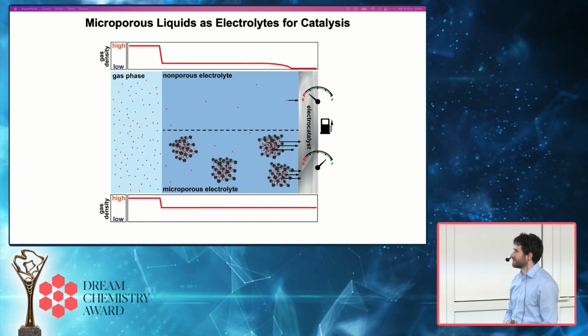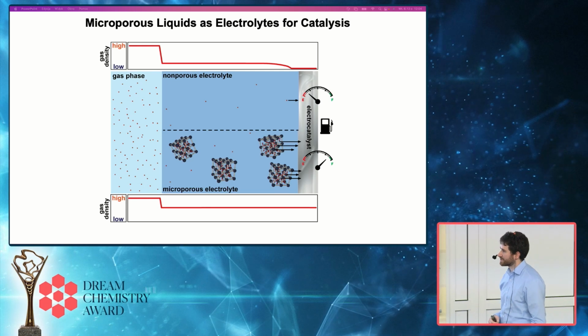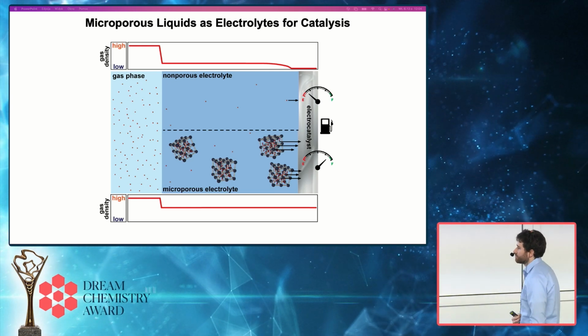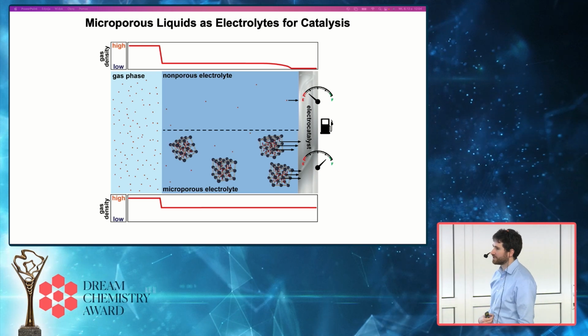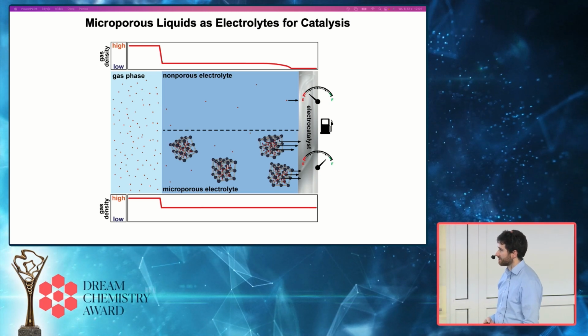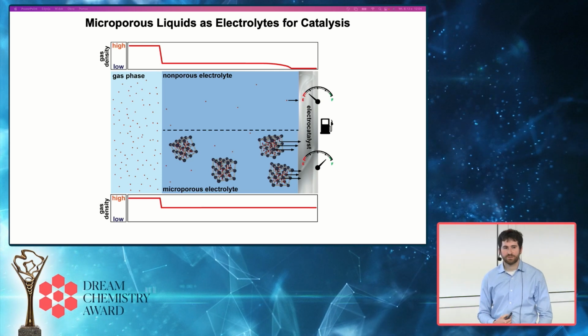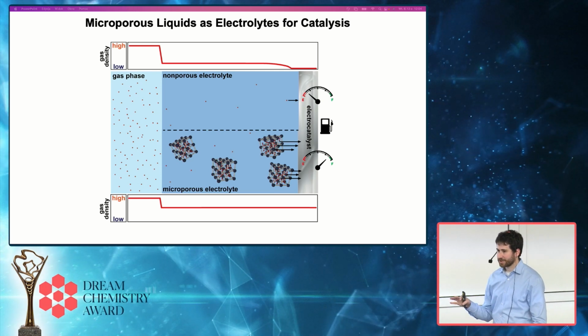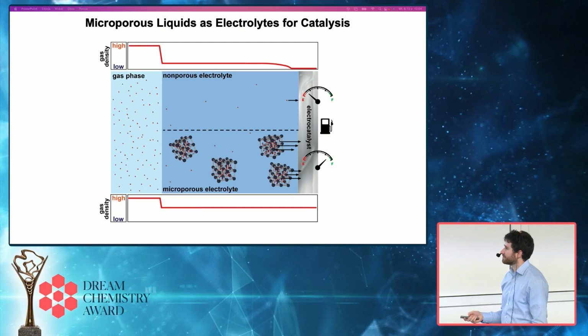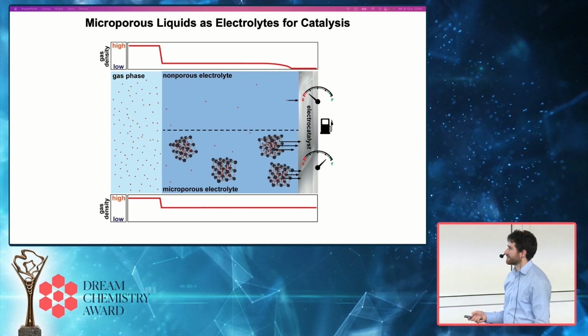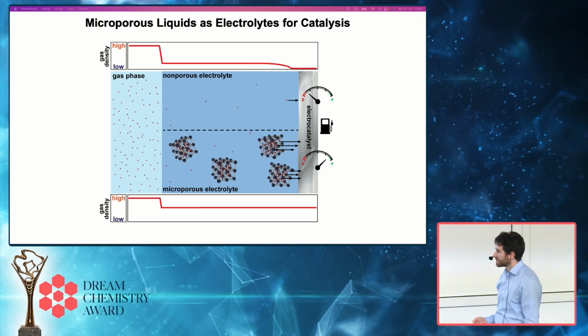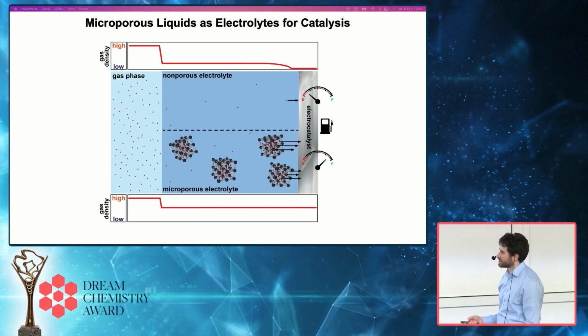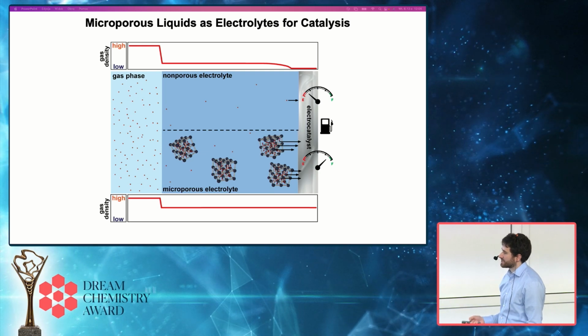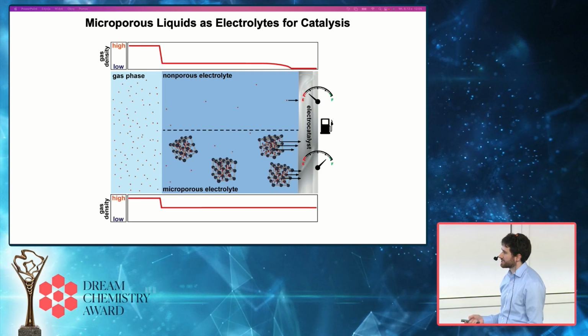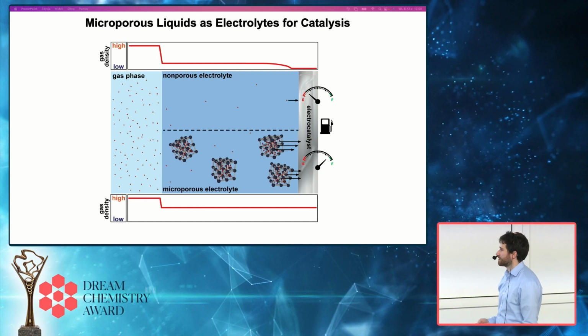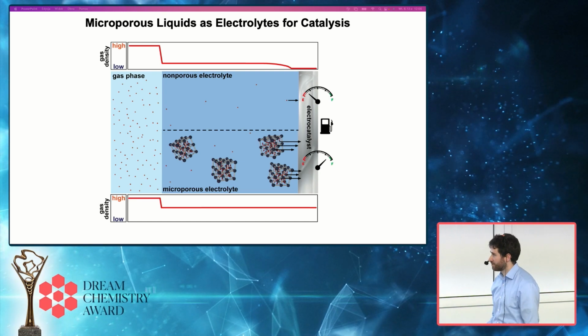One non-biological example that I'll end with, that gets at overcoming some of these gas transport limitations, is some recent work that we've done in collaboration with one of my colleagues in inorganic chemistry at Harvard, Dan Nocera, which was to look at using these solutions as electrolytes for electrocatalysis applications, where similarly we're trying to deal with challenges of transporting gas from a bulk gas phase through an aqueous electrolyte to an electrocatalyst. And our idea was that these porous solutions with high gas densities would basically serve as vectors for transporting gas quickly to the electrode surface, and could overcome some of these mass transport limitations.